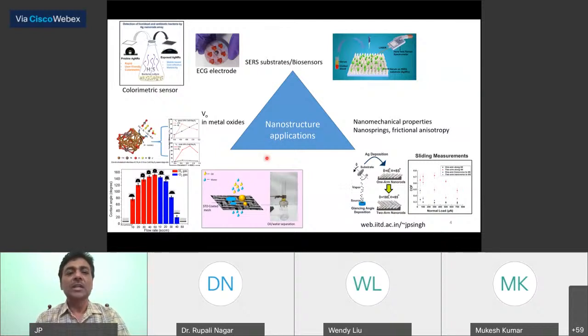Another area we also worked on is oil water separation, which was one application for which we also got a patent. There we showed that if we use these nanostructures, just by using oxidizing or reducing gases like hydrogen and oxygen, we can control the contact angle from 0 degrees to something like 160, 167 degrees, around that. So we can control the wetting properties of these nanostructures.